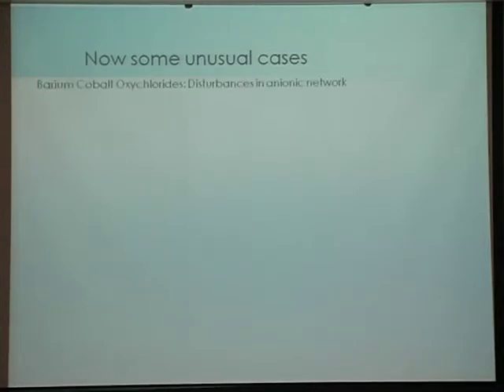The first case is this. Unlike many people here, I myself try to create disturbances in the system. That means I try to plan systems. Here, the compound is barium cobalt oxychloride. That's basically barium cobaltate, BaCoO3. And the previous speaker already said that in presence of barium, most of the time your tolerance factor is high and you get a 6H or hexagonal structure stabilized.